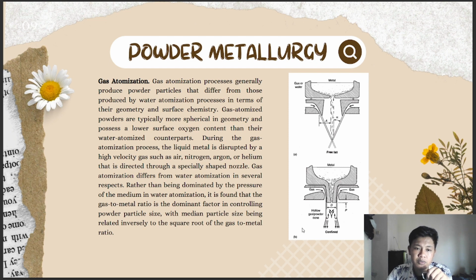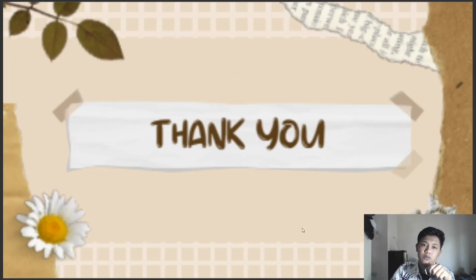During the gas atomization process, the liquid metal is disrupted by a high-velocity gas, such as air, nitrogen, argon, or helium, that is directed through a specially shaped nozzle. Gas atomization differs from water atomization in several respects. Rather than being dominated by the pressure of the medium as in water atomization, it is found that the gas-to-metal ratio is the dominant factor in controlling powder particle size, with median particle size being related inversely to the square root of the gas-to-metal ratio.